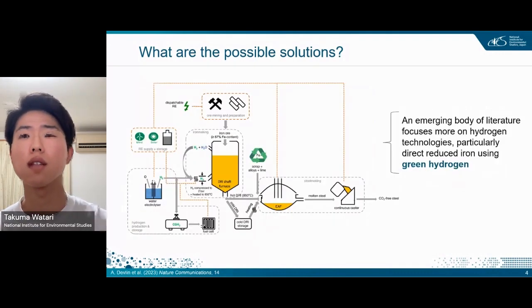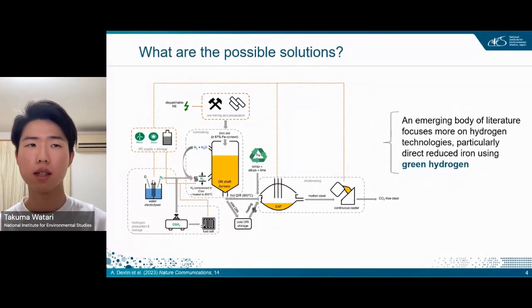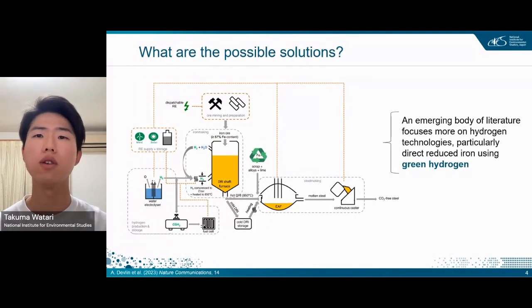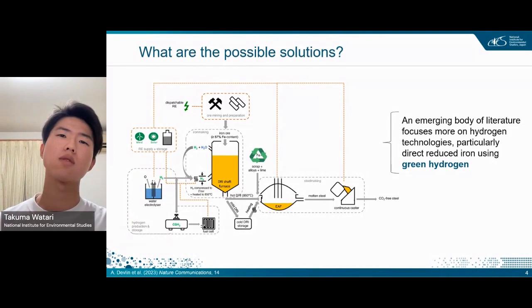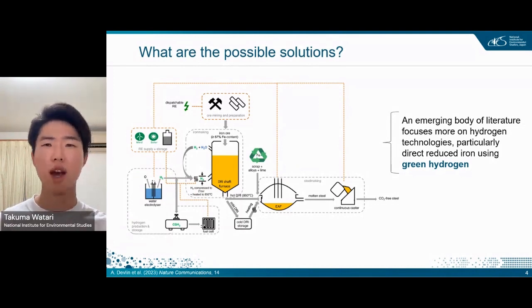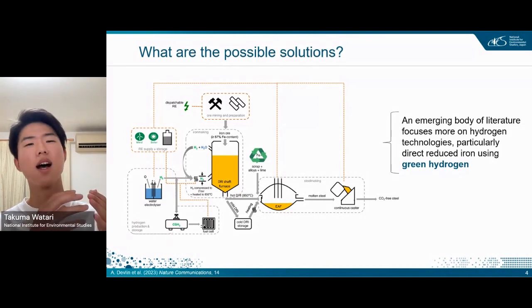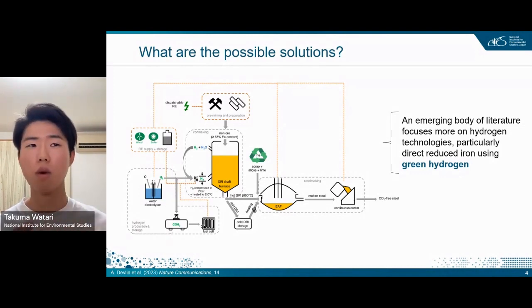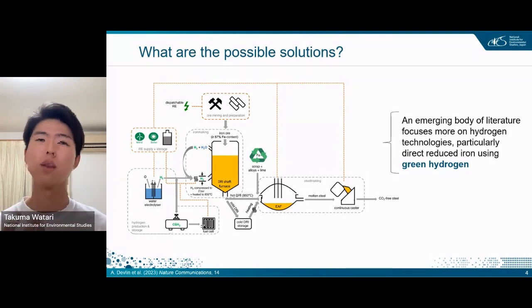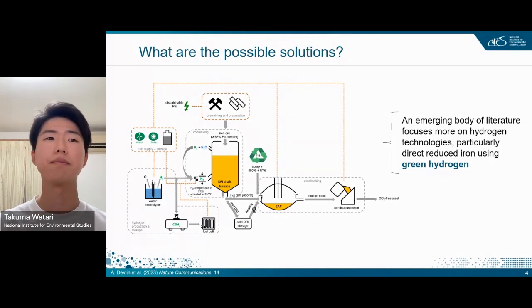In addition to CCUS, an emerging body of literature focuses more on hydrogen-based solutions, particularly direct reduced iron using green hydrogen. What this technology is trying to do is reduce the iron oxide ore using hydrogen instead of coke. The idea is that if we use hydrogen to remove the oxygen from the iron ore, then all that comes out is water, not CO2. That is the basic idea, and we have quite a lot of research in this space. A recent study indicates that hydrogen-based steel can be economically competitive when combined with high-quality iron ore and also abundant and cost-effective renewable electricity.